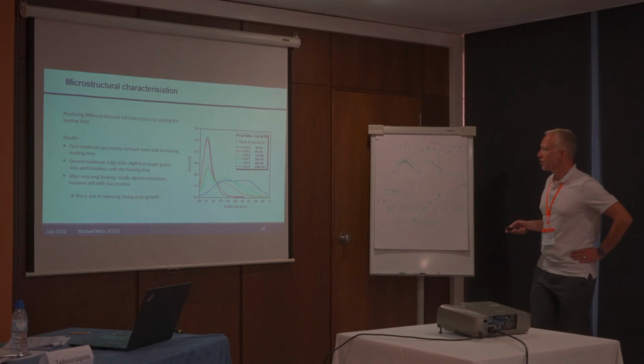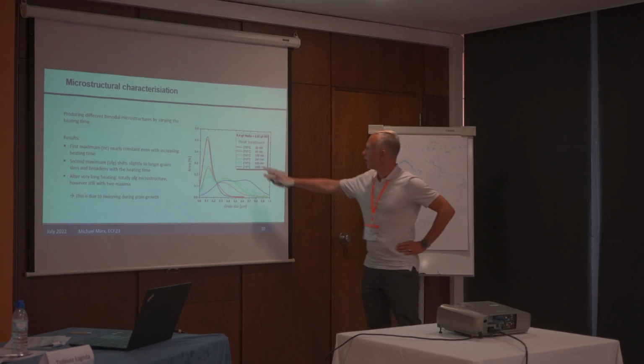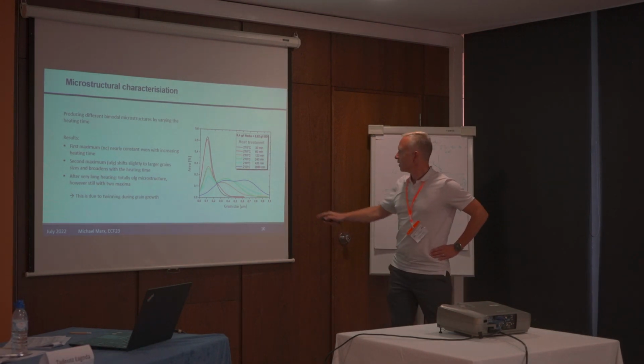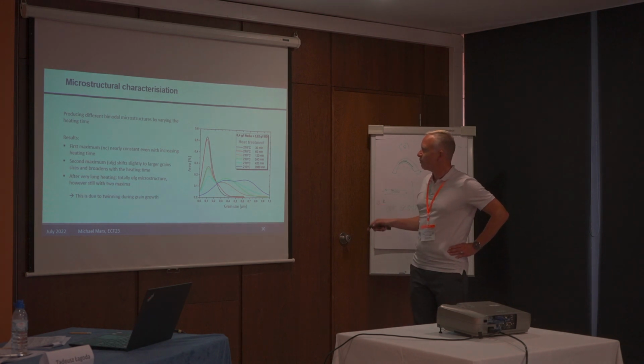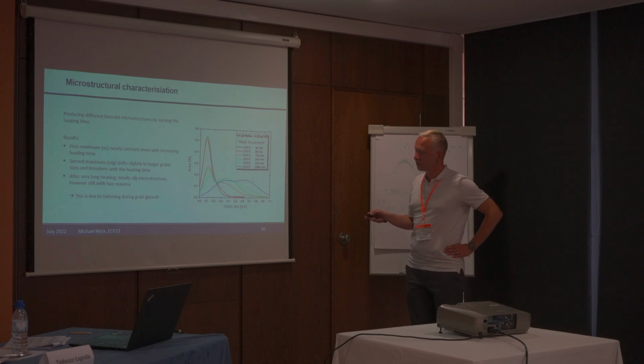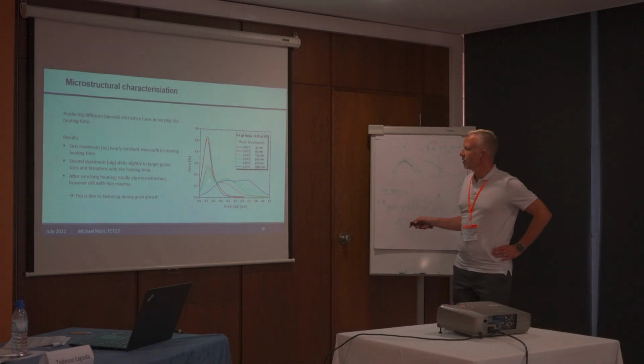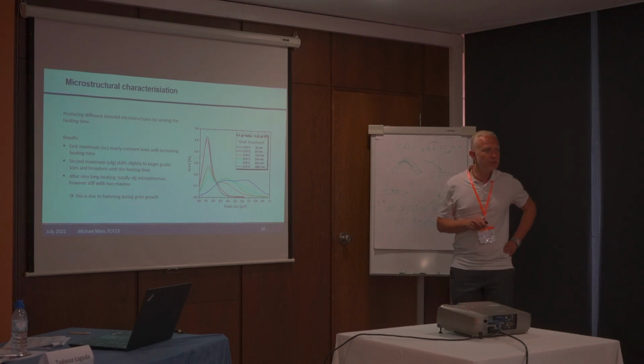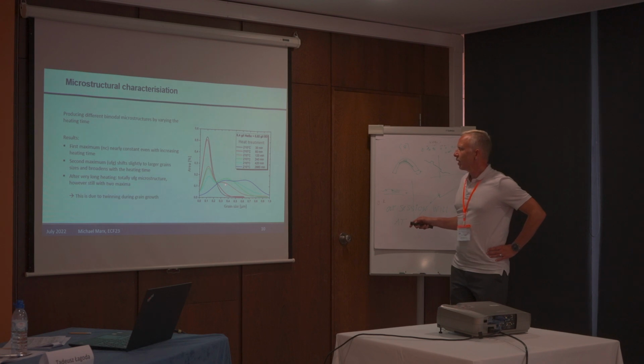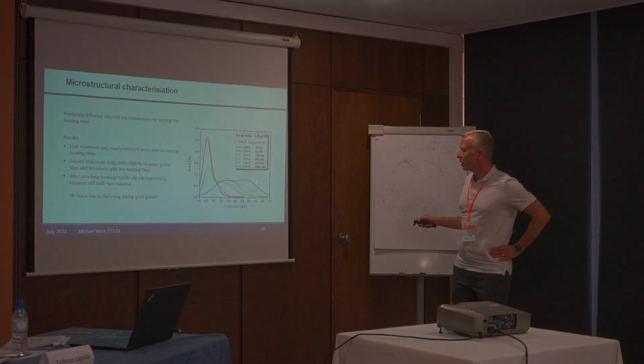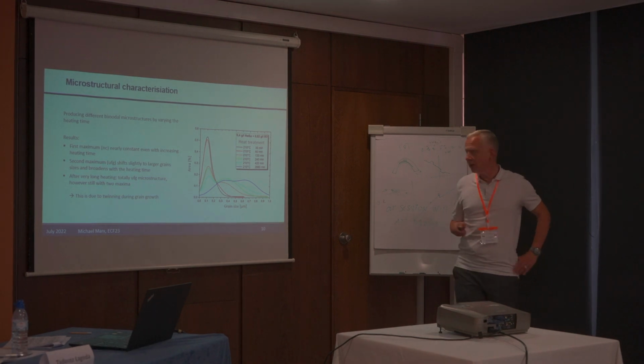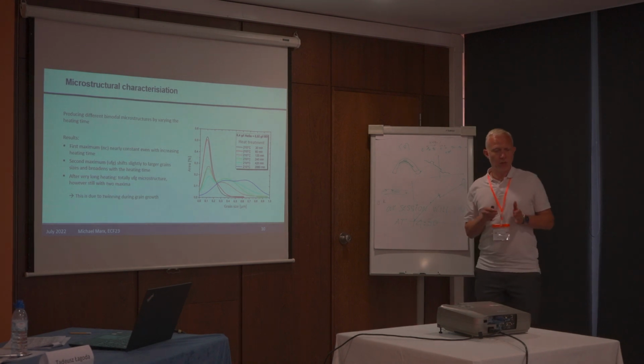This is the microstructure for different heat treatments, 210 degrees C for different times. The blue curve is for very, very long time, and the first maximum here in the nanocrystalline area remains nearly constant. The ultrafine grained maximum shifts a little bit to higher grain sizes, but it's also in the area. Again, this must be nanometers here, not micrometers. Sorry for that. And after this long time, you get still some bimodal microstructure, but in the ultrafine grained region. This is due to twinning during the grain growth. The other one is because of this abnormal grain growth.